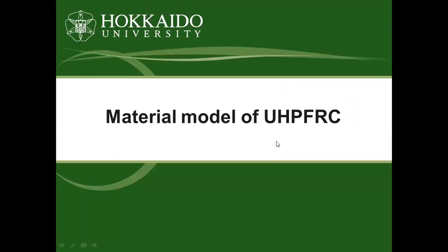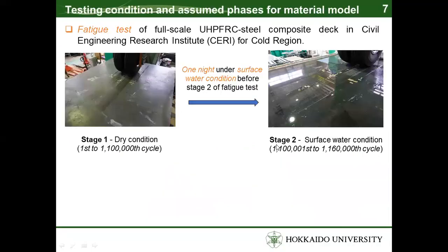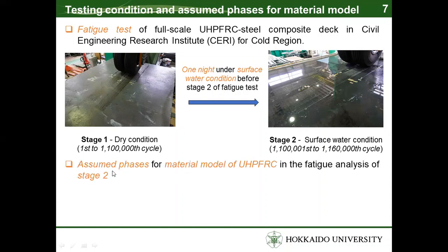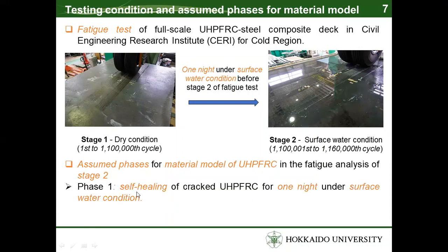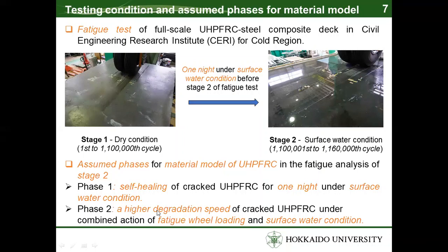Material model of UHPFRC. After the first stage under dry conditions, water has been supplied on top surface of UHPFRC for one night before stage 2. Assume two phases for the material model of UHPFRC. The first phase is the self-healing of cracked UHPFRC for one night under surface water conditions. The second phase is a higher degradation speed of cracked UHPFRC under combined action of the fatigue wheel loading and surface water conditions.